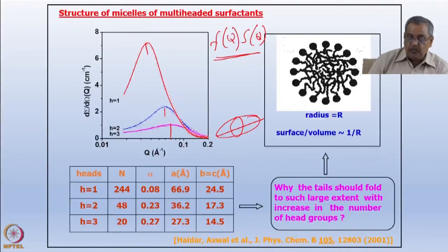I want to point out to you that I am dealing with length scales which are much larger than crystallographic length scales, but I am able to predict interparticle distance like I did in the case of atomic liquids and molecular liquids for liquid and amorphous diffraction. From there I can find out the particle size by fitting the models for a prolate spheroid. So this is a finding in SANS where I can find out the shape of the particles and also their interparticle distance. This was also an example from what we did at Dhruva.